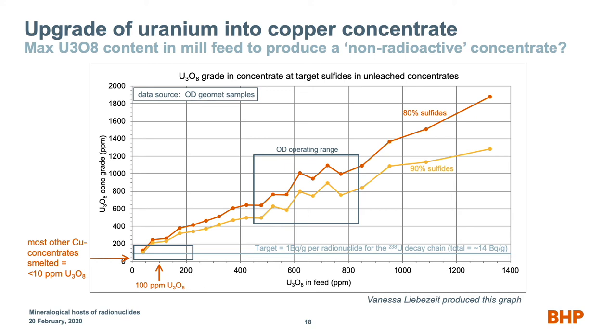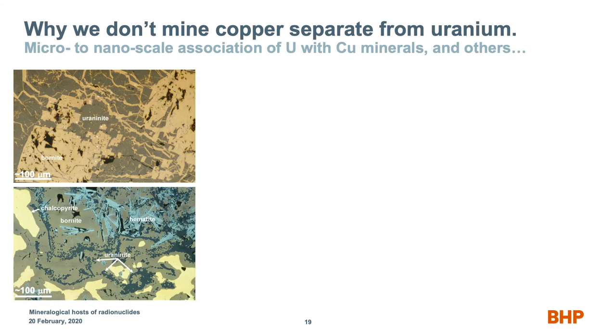In order for us to make a material that's less than 1 becquerel per gram per radionuclide, we need to be down here, and we need to be making a concentrate somewhere down around that box. The only way that we can make a concentrate from Olympic Dam material that's down around that box is to mine material that probably has a grade somewhere around there. Okay, remember that. Most smelters in the world, the vast majority, except for a few, actually process concentrates that have less than 10 ppm of uranium in them. So just keep that in your mind.